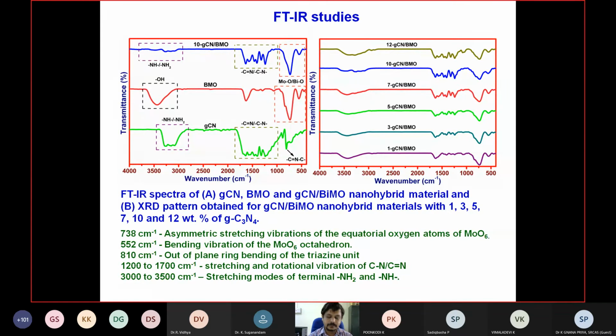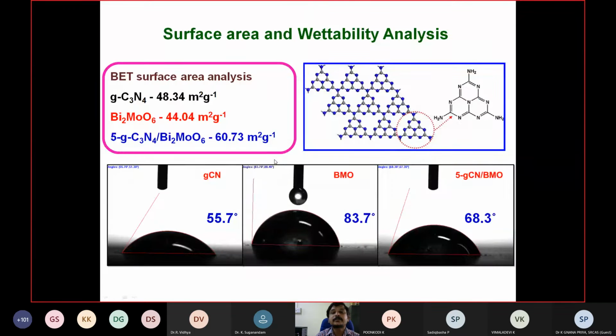There we found different functionalities like carbon-nitrogen double bond, carbon-nitrogen single bond, as well as metal-oxide linkages, and then the amine group. Those functionalities we have confirmed with these FTIR studies. We have given the explanation here of which peaks appeared due to which functionalities. And this is the crucial result obtained for our material.